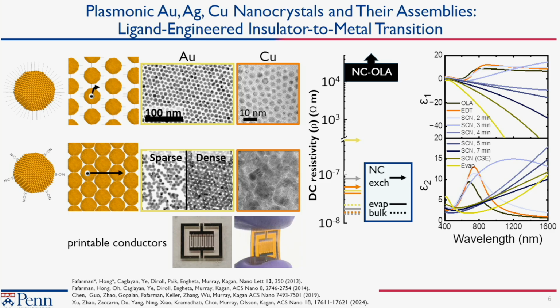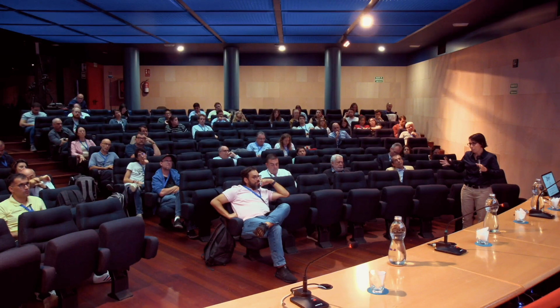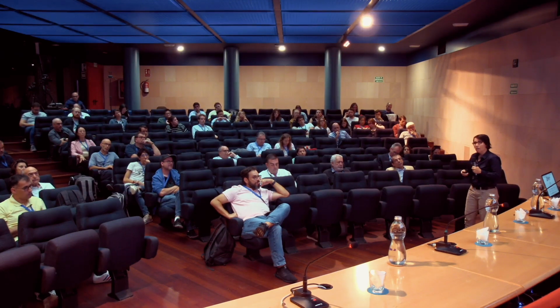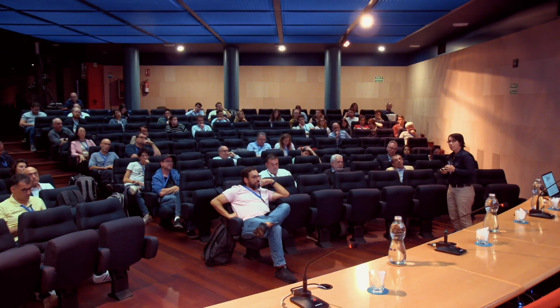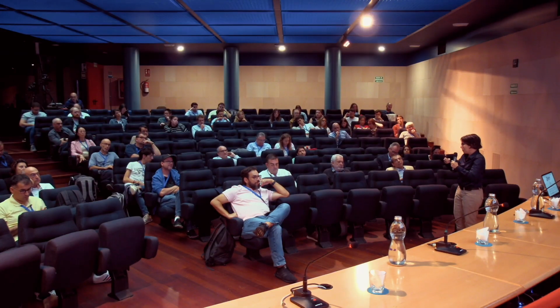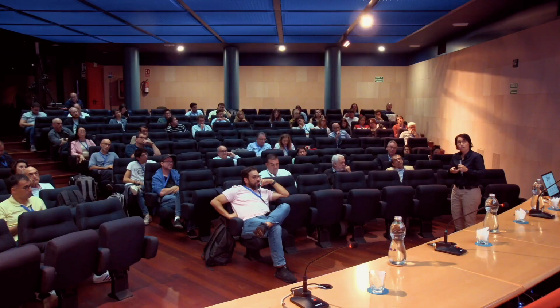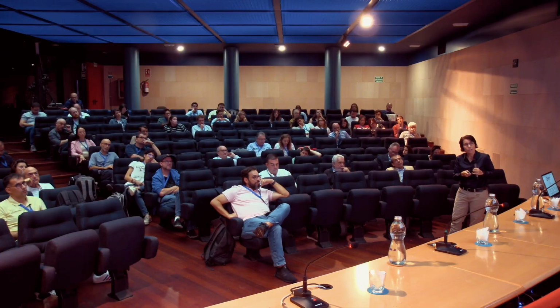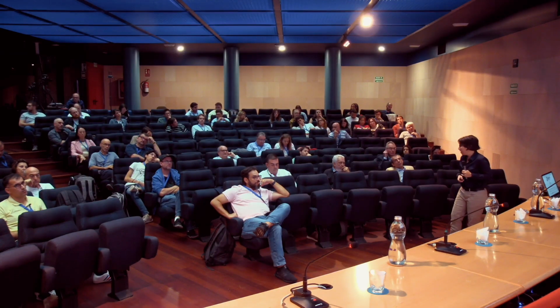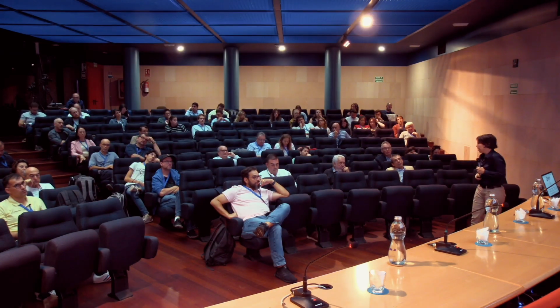And this is something we know fairly well for particle systems. If you start to bring these particles close together, you can sort of dial in the dielectric function. As you bring them closer and closer together, which we can do by control of the concentration of the ligand that we swap, you watch the real part of the dielectric function slowly go from being positive to everywhere negative, characteristic of a Drude-like metal.